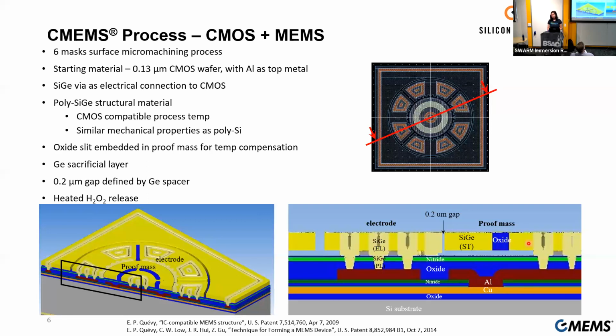On the right side, that is the proof mass. The proof mass also has a similar electrical connection to the aluminum top metal. And then embedded in the silicon germanium structure, we have this oxide for temperature compensation.